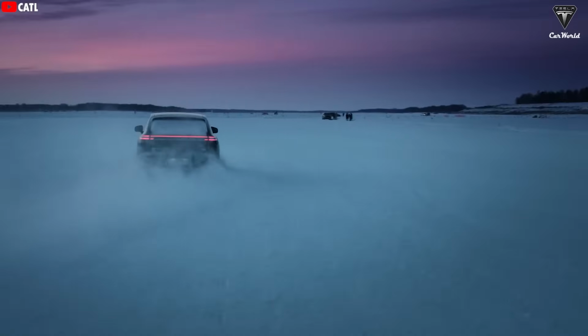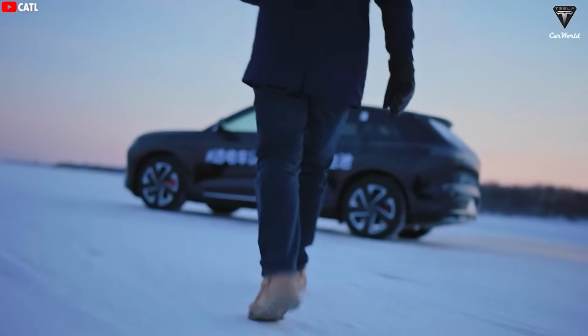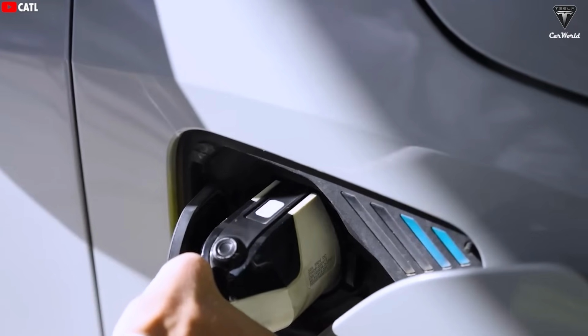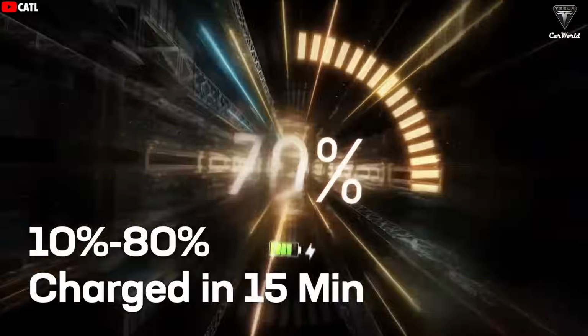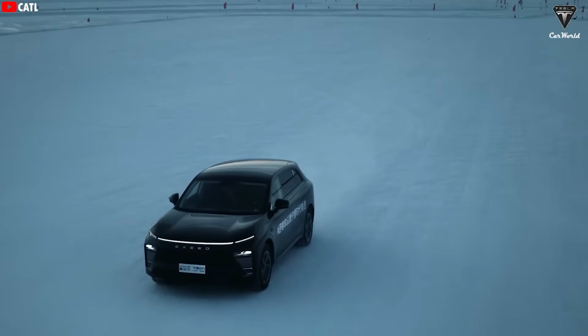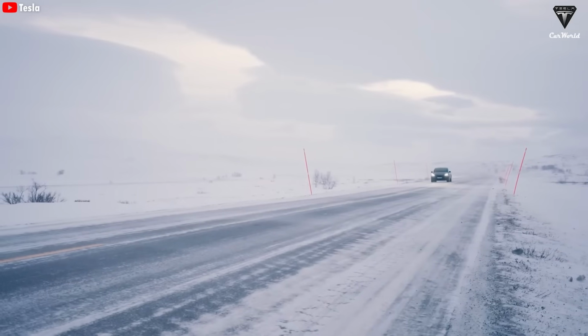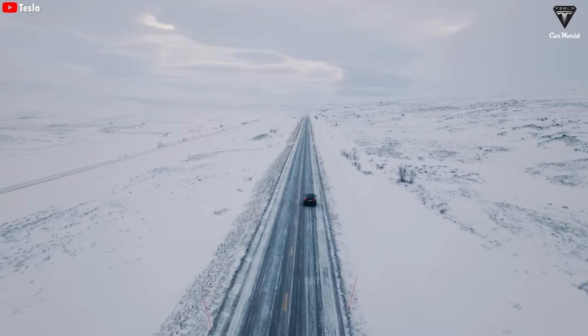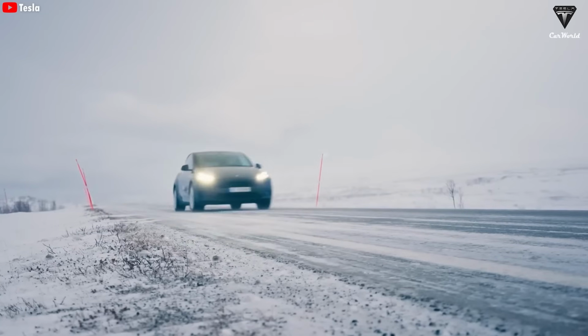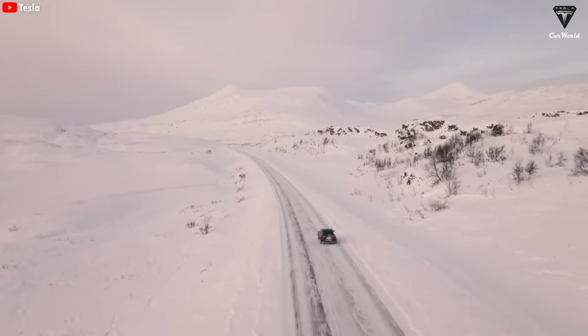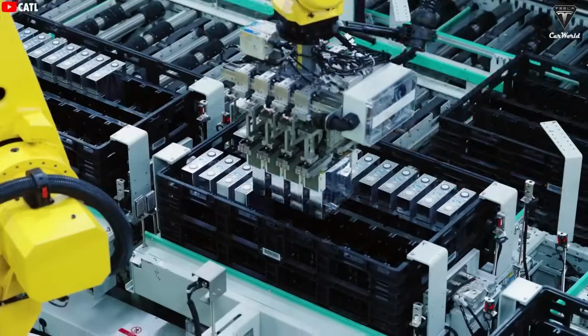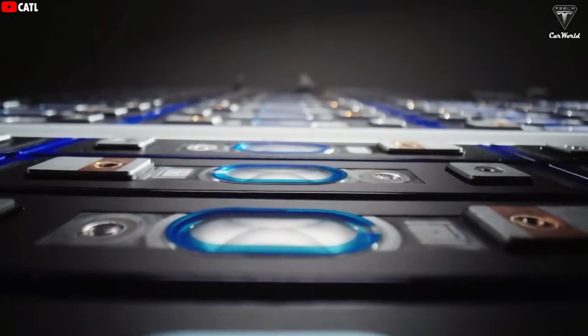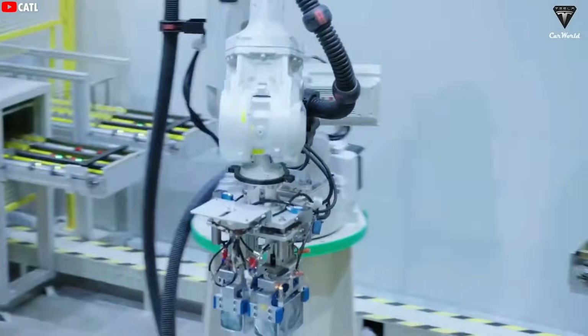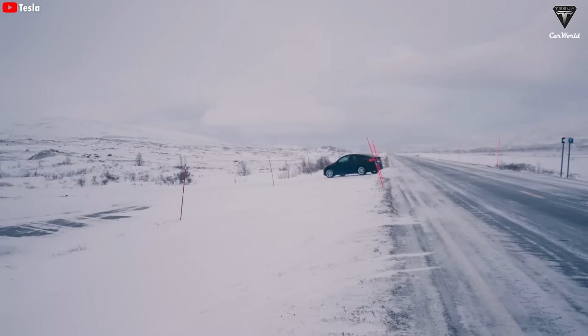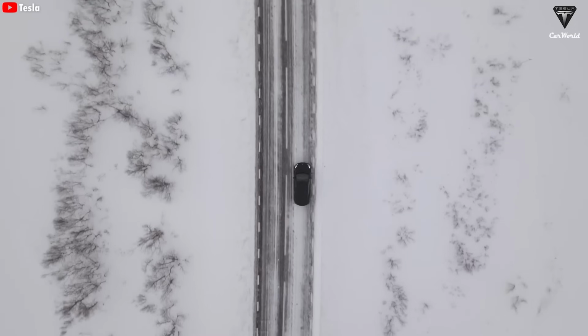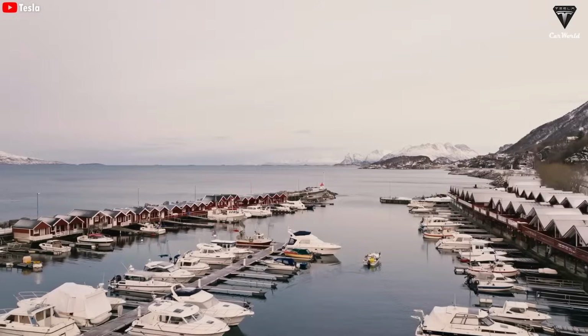One standout advantage of sodium-ion batteries that we particularly value is their ability to maintain stable performance at low temperatures. Many have demonstrated that they can still charge from 10% to 80% in just 15 minutes, even at -10 degrees Celsius. This makes sodium-ion batteries an ideal choice for regions with harsh winters or cold environments, where EV performance degradation during winter is one of the main reasons many consumers are still hesitant to adopt electric vehicles. Therefore, Naxtra batteries may shift public perception and spark a revolution by offering minimal capacity degradation at low temperatures and functioning efficiently in extreme cold down to -40 degrees Celsius. The so-called winter range anxiety for EVs might soon fade away.